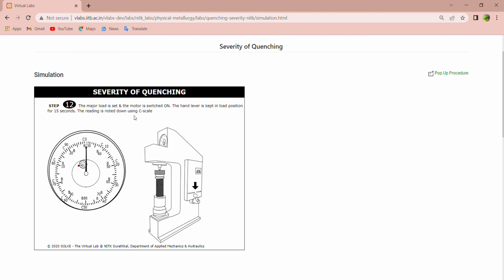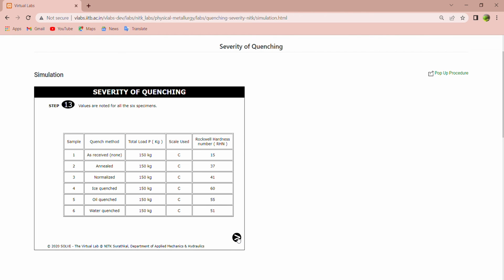The major load is set and the motor is switched on. The hand lever is kept in the load position for 15 seconds. The reading is noted down using the C scale. 15 seconds, until the red dot. Then unload it. Here you can see the values are noted for all the 6 specimens.